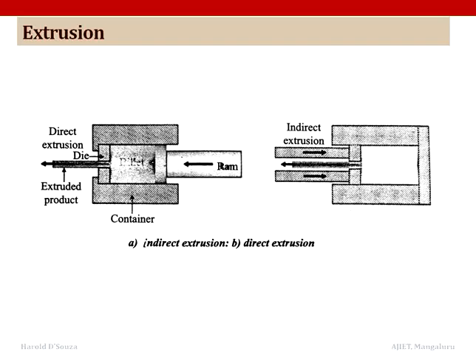Powder extrusion at higher temperatures is similar to compact material processing. An initial material is in a form of a pre-compacted or a pre-sintered material. To avoid oxidation and contamination from the extrusion process, lubricants, the material can be canned to a container of a mild steel plate. Now, this method allows reaching high density for such materials which have oxide coatings by reason of high affinity for oxygen. Therefore, they are difficult to sinter. For instance, aluminium, magnesium, titanium, high speed steels, etc.